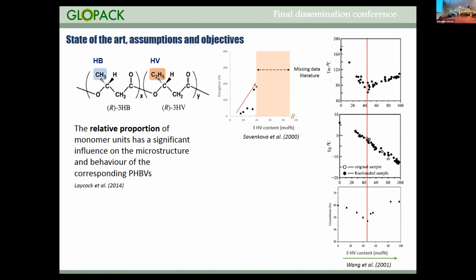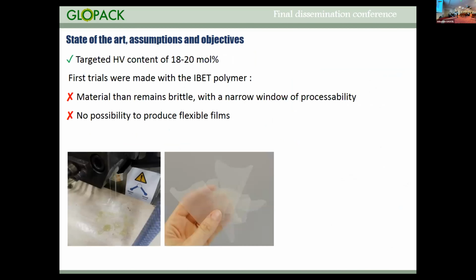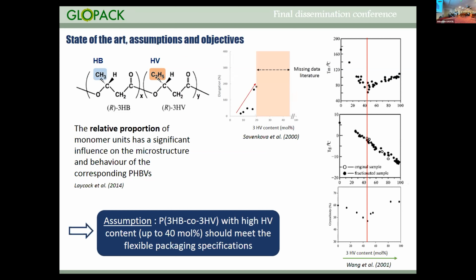You see that if you increase the HV molar content, you decrease the melting temperature, up to an HV content of 45%. You also decrease the crystallinity and you decrease the glass transition temperature. And also, if you increase the HV content, you can increase the elongation at break. The elongation at break corresponds to the maximal deformation that the material can display when it is elongated. So if you want to reach flexible materials, you will want a high elongation at break. So based on this state of the art, we made the assumption that reaching a high HV content would meet the flexible packaging specifications.